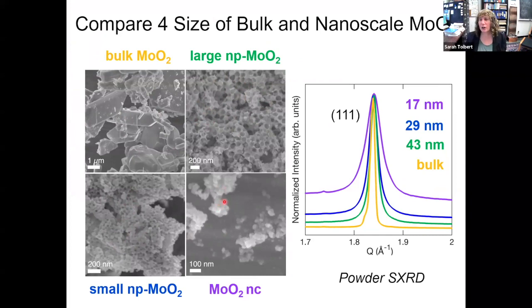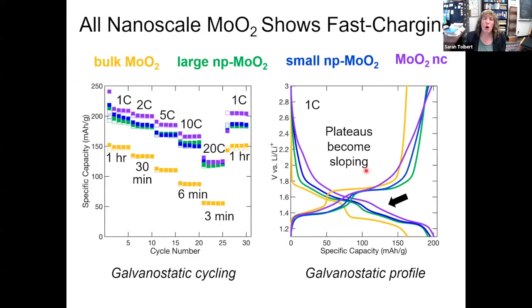These are not a perfect architecture. They're not interconnected, but they're the only way to make it really small. And for those of you who know X-ray diffraction, we see that the peak widths steadily broaden as we make our material smaller.